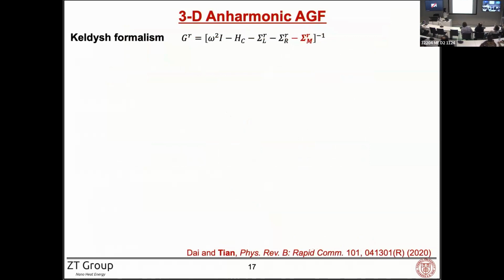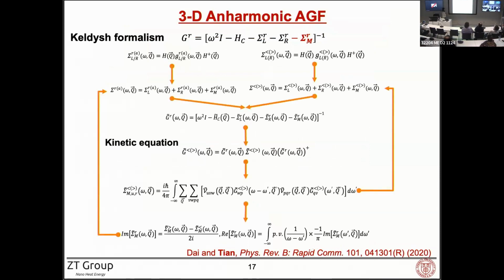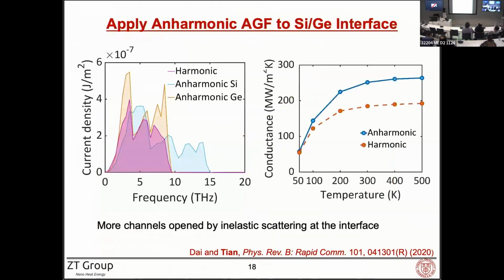Now you notice here I have one extra term compared to the harmonic Green's function. This is a many-body self-energy term, which essentially describes the phonon scattering. We need to calculate this many-body self-energy iteratively. We reformulated everything in the reciprocal space. By solving this many-body self-energy iteratively, we are able to include the inelastic scattering effect. One example here is for a single silicon-germanium interface. If we only have the harmonic contribution, basically only the phonon frequencies which overlap between silicon and germanium, we can have the phonon propagation marked here in pink.